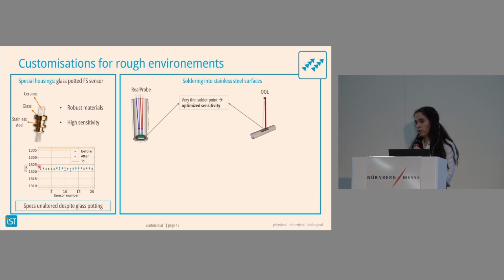Another possibility, when nothing should contact the sensor or vice versa, the media should not be contacted by anything, is to solder the sensor on top of stainless steel surfaces. And this is what we have here as an example for the RealProbe. So here this is a temperature sensor soldered on the bottom of this tube.